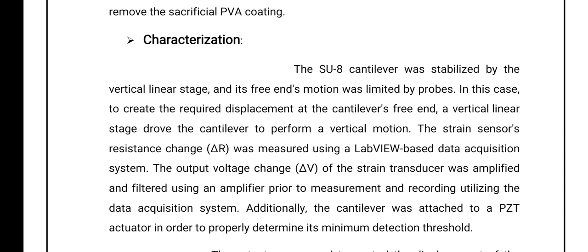Basically, there is a linear relationship between the displacement applied to the cantilever and the change in sensor resistance. At 10 micrometer and 100 micrometer displacement, the sensitivity change rates were 1.33 × 10^-4 and 12.38 × 10^-4 respectively. When the applied load was removed, the silicon sensor returned to its initial state without significant hysteresis, meaning delay in response.